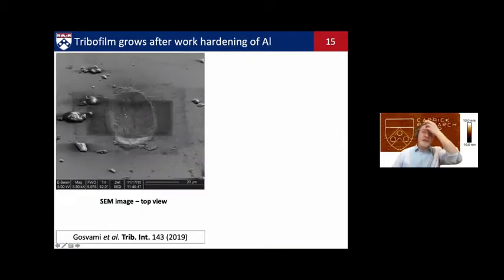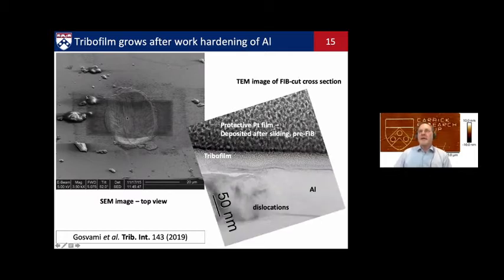And when we look at it in the SEM, indeed we see that we have damaged the substrate. So what you can see, this is where we were sliding with the AFM tip. And I should have mentioned, we used a large colloidal probe. So this is a much larger contact than a typical sharp AFM tip. So we used a microcolloid. We slid back and forth. You can see a lot of plastic damage on the substrate, a dish-shaped indentation here, as well as a buildup of material, which is the tribofilm.